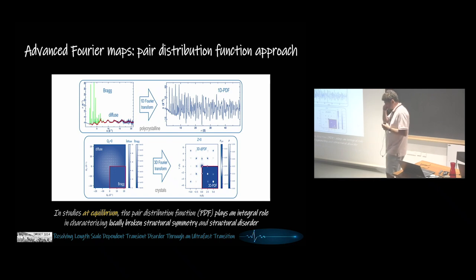More recently, you also have a single crystal version of this, which is essentially called the 3D pair distribution function method, in which you collect maps over very broad Q ranges, and then due to the fact that those signals are of different type, you can punch out Bragg, and propagate only the diffuse scattering signal, which you then 3D Fourier transform, and you end up with a map, which is called 3D differential PDF, which gives you information on how your atoms are deviating from the crystallographic structure. So what we wanted to do is to bring this logic and this methodology into the ultrafast regime, to be able to move forward the nanoscale characterization.